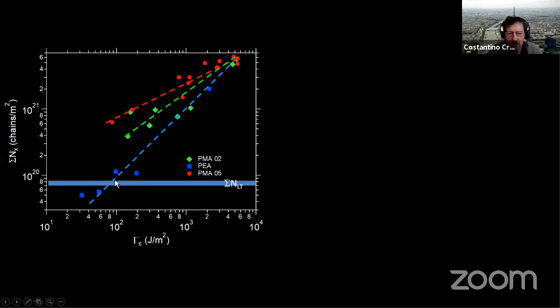Now you can see that indeed the energy due to bond scission increases with rate and increases at different rates depending on the material. The red one is the more cross-linked high Tg one, the blue one is a low Tg, and the green one is the less cross-linked. So there's definitely a coupling between the viscoelastic behavior and the network structure, which for us was a surprise. I'm not saying we understand it, but it's something that we are really looking into. As I said in the introduction, I'm quite curious to see how you can affect macroscopic properties with molecular structures. And so here we learn something about which molecular structure works better than others.